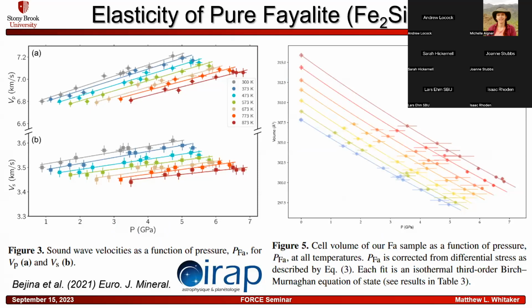So we also have done some work on the elasticity of fayalite, and this was published a couple years ago in the European Journal of Mineralogy. We can see that the sound wave velocities as a function of pressure are shown here in the plot on the left. And the unit cell volume of the fayalite sample is given as a function of pressure at all temperatures in the plot on the right.